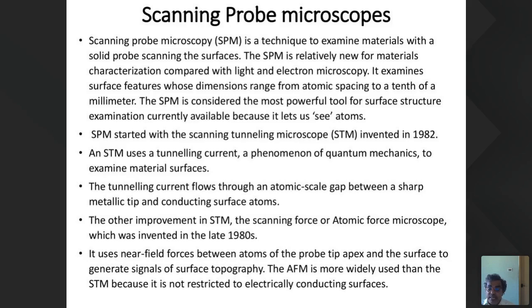The other improvement on STM is the scanning force microscope, recently renamed as the atomic force microscope. It was invented in the late 1980s. It uses near field forces between atoms at the sharp tip apex and the surface to generate a signal of surface topography. The AFM is more widely used than the STM because it has no restriction on conductivity. It is not restricted to electrically conductive surfaces, so it has wider applications compared to the scanning tunneling microscope.